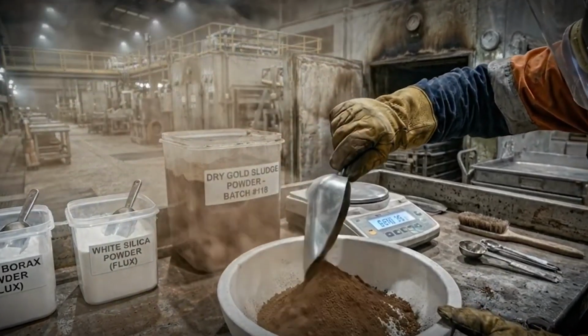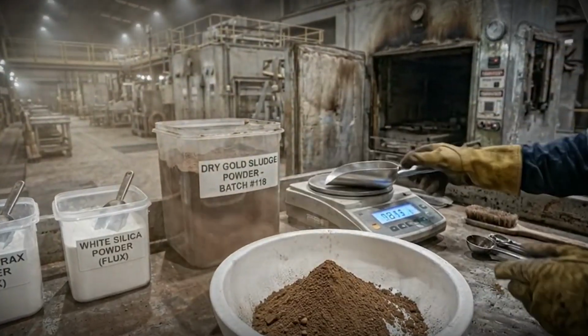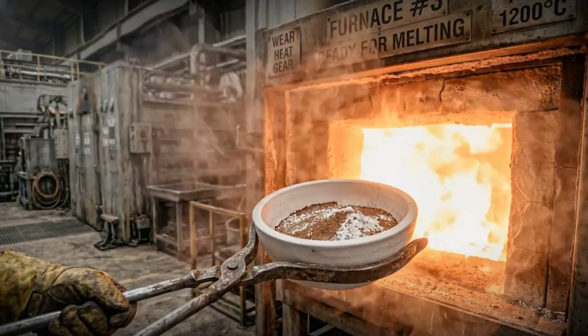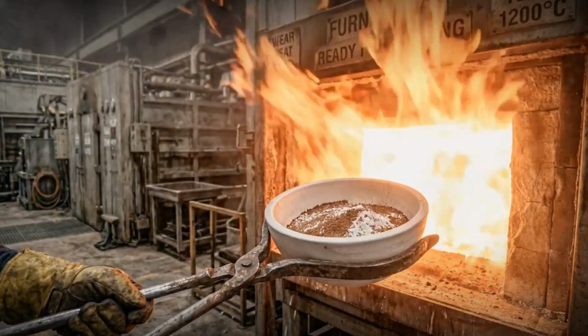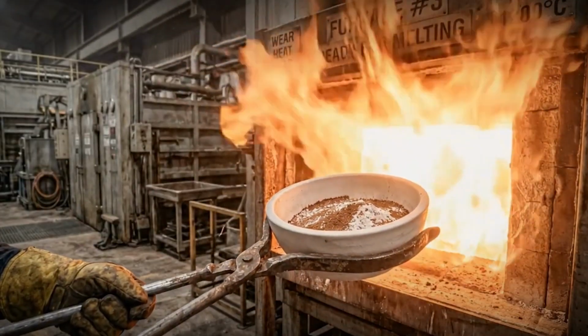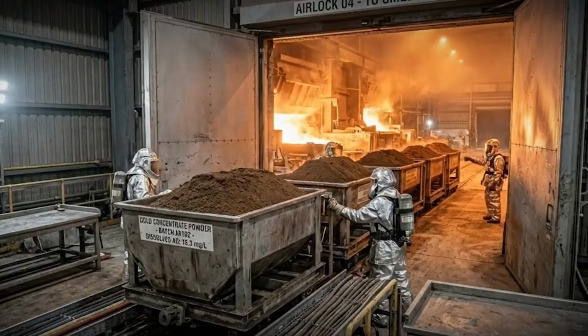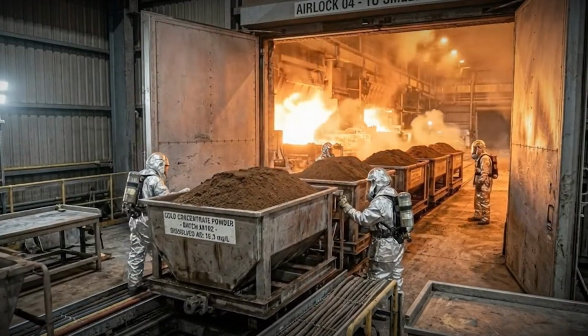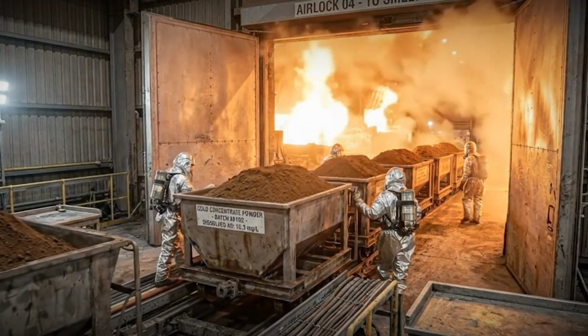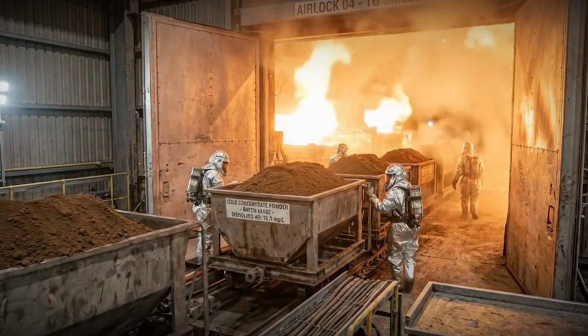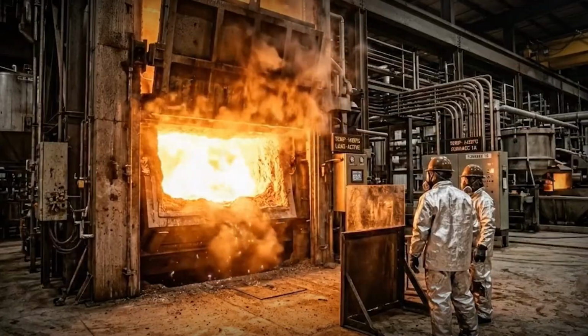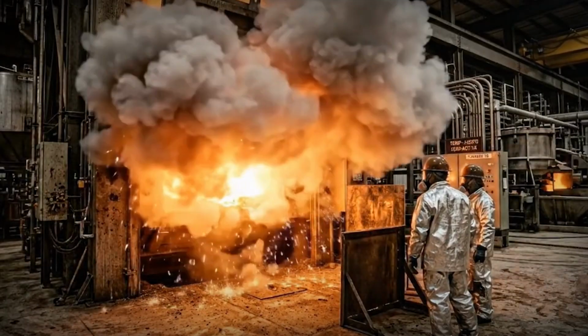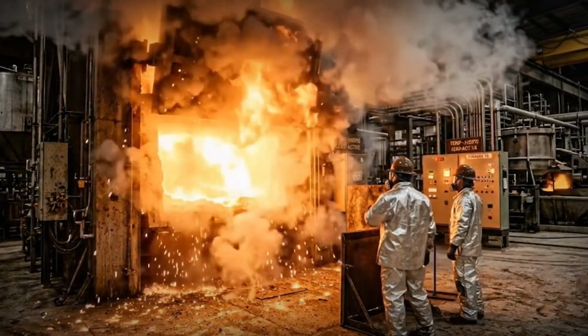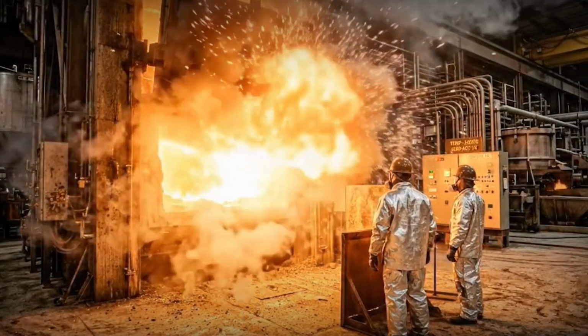The result is a doré bar, an alloy of gold and silver, typically containing 60 to 90% gold and weighing around 20 kilograms per bar, still not pure, but now a tradable, transportable form of precious metal worth hundreds of thousands of dollars each. Every doré bar is stamped, weighed, and logged, traceable from the mine pit it came from to the vault it will eventually reach. But even this isn't the end.